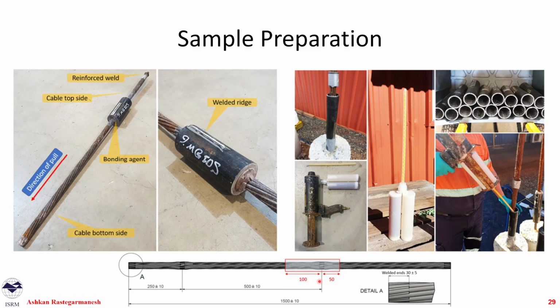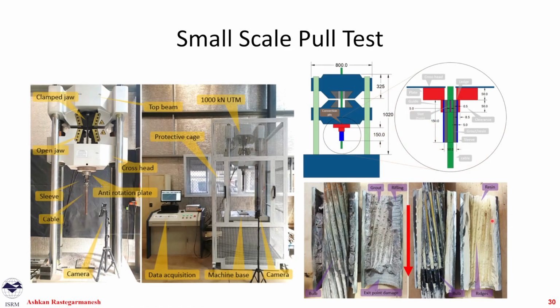In terms of the location of the bolt, we wanted to have enough utilization of the length of the bolt. So we had the 150 located in a way that we have 100 millimeters of displacement. So once we pull out the cable in this direction, we actually have the bolt moving through our annulus for at least 100 millimeters. And on the right, you see the resin injection. Again, this was a two-part resin, which had the air gun, which would get mixed with this straw, and then we inject the embedment length that we wanted to pull the cable out from.